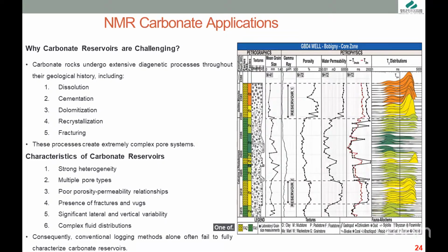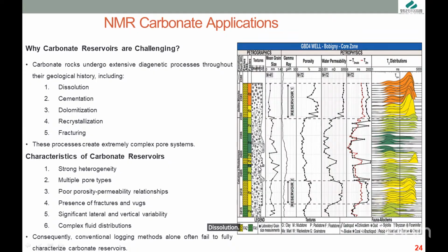One of the most important applications of the NMR: why are carbonate reservoirs challenging? This is the question. This is an example from well GBD4. It's probably a core zone. Actually, what you find here is that the carbonate was different, from the core data and the texture on it. Carbonate rock undergoes extensive diagenetic processes through its geological history, including dissolution, giving a highly heterogeneous pore system. It's unlike the sandstone. It is just a complicated reservoir, and it is very challenging. NMR addresses the challenge by directly measuring the fluid within the pore system rather than relying on the bulk rock properties.